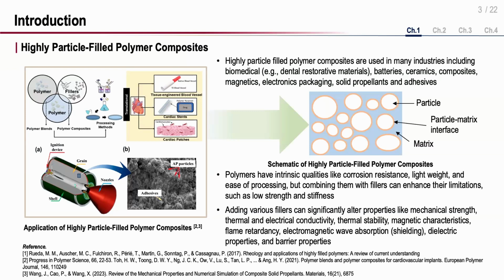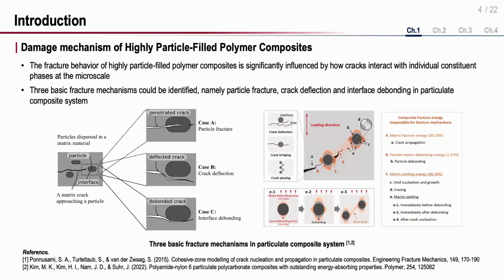Adding various fillers can significantly alter properties. But at this point, it is necessary to focus on the fracture behavior caused by high particle filling. The fracture behavior of HPFPC is significantly influenced by how cracks interact with individual constituent phases at the micro scale. There are 3 basic fracture mechanisms. First one is particle fracture, second one is crack deflection, and third one is interface debonding. In particular, understanding the behavior of interface debonding is important because it significantly affects the energy absorption, fracture resistance, and load transfer efficiency.